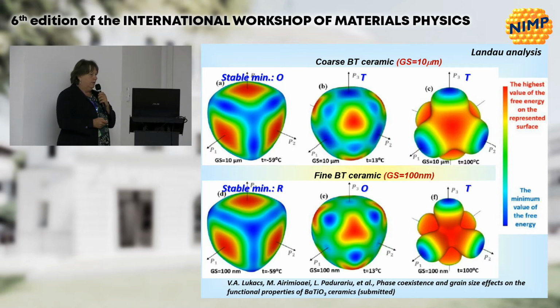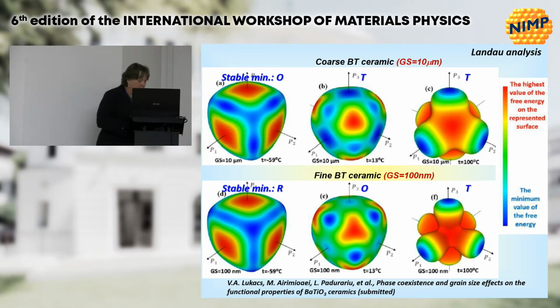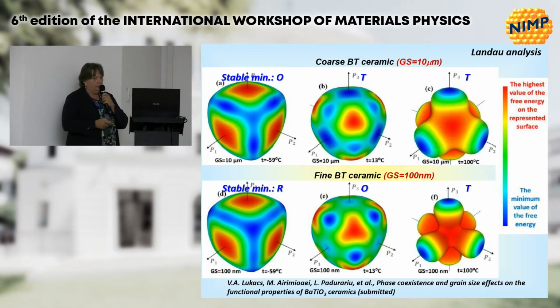There are some simplified Landau calculations, and Leontin Pădurară, our colleague, performed Landau-based calculations for ceramic materials, for ceramic barium titanate, in which he looked not only to the stable minimum, to the absolute minimum of the free energy, but also to the metastable states, to the other minima. And practically, he found many ranges of phase coexistence, which were not reported before.